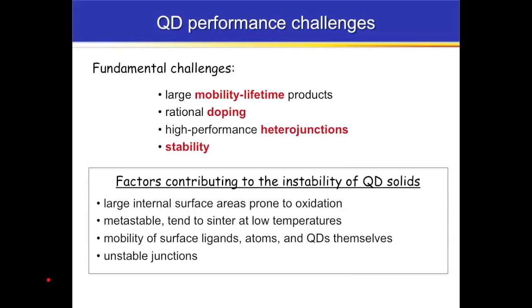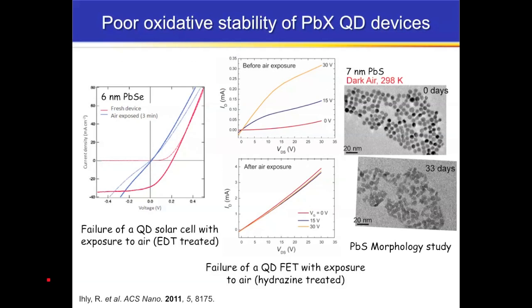They're also, because they're high surface energy, metastable objects. They're little dots that want to grow into big spheres. And so they tend to sinter at very low temperatures, even less than 100 degrees C in some cases. And so we obviously need to stop that kind of stuff from happening if we're going to make a device that actually persists for any length of time.